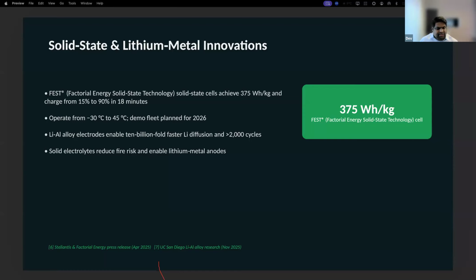So solid state battery is pursued by a number of commercial car brands and other commercial companies as one of the major breakthrough battery technologies in the near future. University of California, San Diego researchers developed a lithium aluminum alloy anode that allows lithium ions to diffuse up to 10 billion times faster by controlling the beta phase within the alloy. So their solid state cells maintain high capacity over 2000 cycles, demonstrating the potential for long-lived lithium metal batteries.